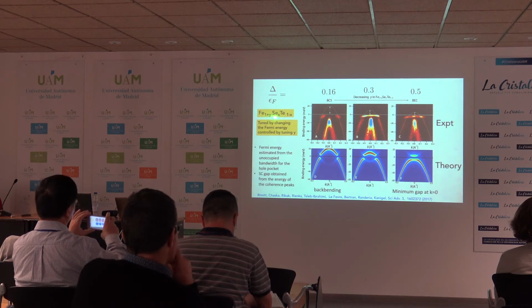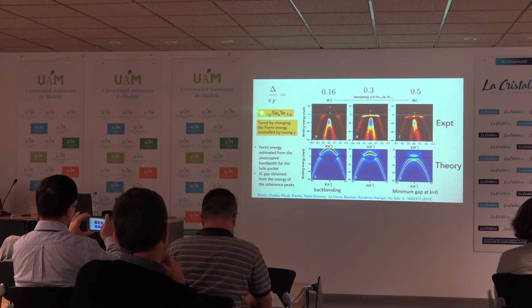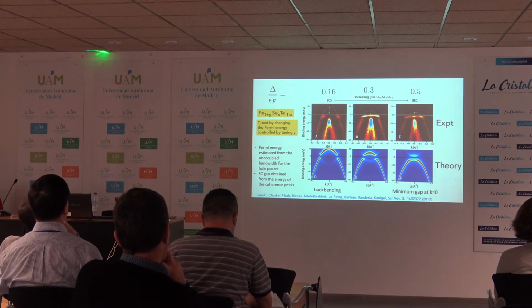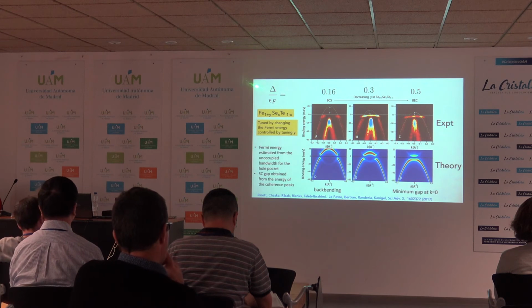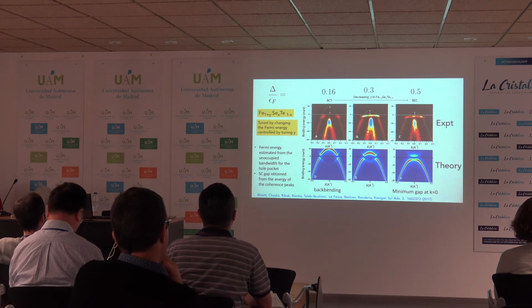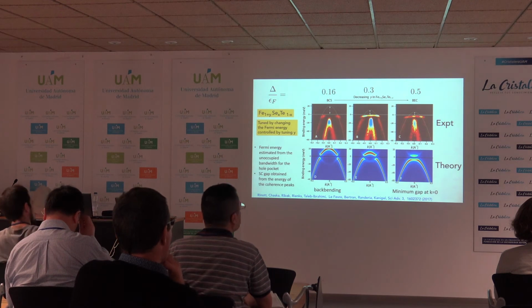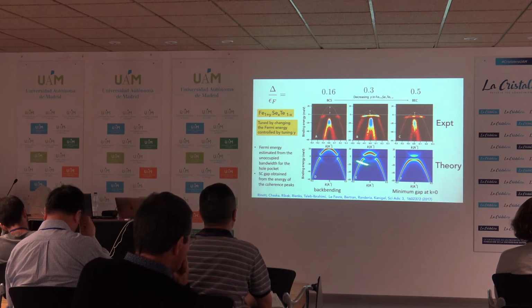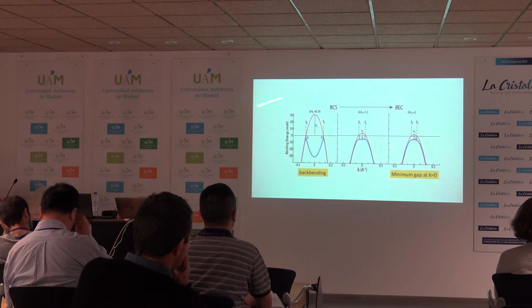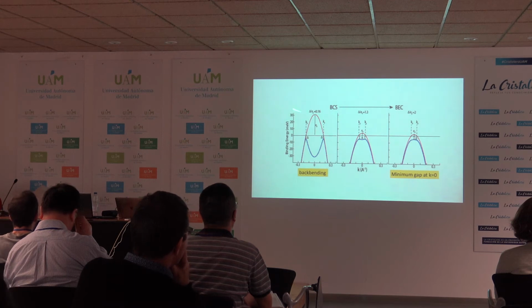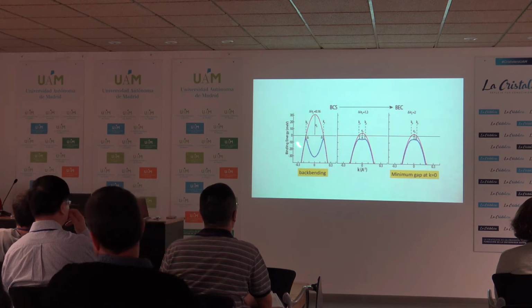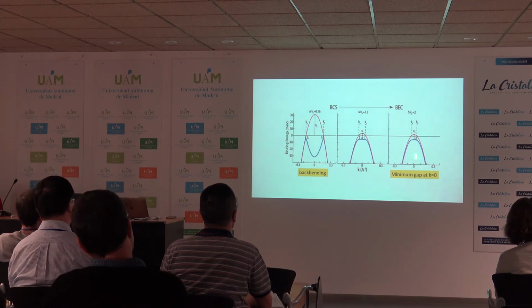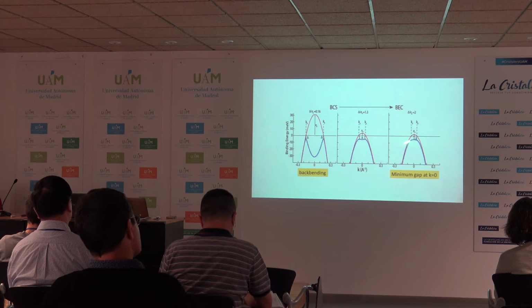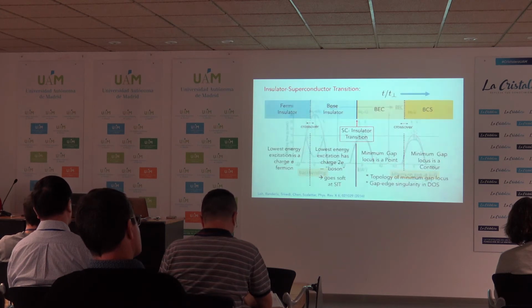What was done in these experiments was to use iron concentration to tune the Fermi energy. So in that way, rather than making delta large, they were able to make EF small and thereby increase delta over EF from 0.16 to 0.5. And you can see that, in fact, this is the spectra at the two levels. And here is a fit which shows very clearly that when delta over EF is small, 0.16, the backbending happens at some finite KF. And here, when you go toward the BEC regime, the minimum of the gap is at the gamma point.